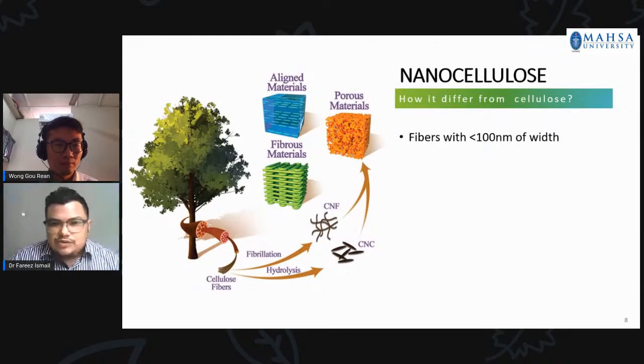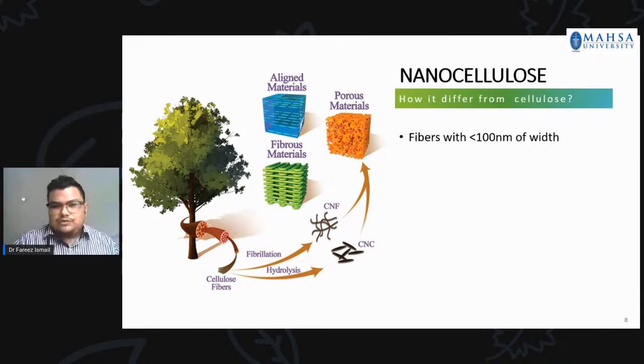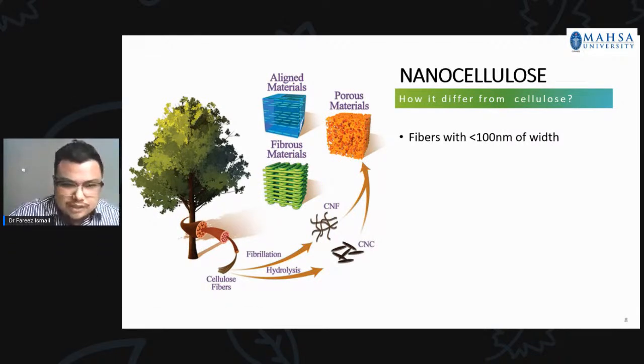So now looking at nanocellulose, how does it differ from cellulose? Looking at the image here, a single plant cellulose fiber, with a width of 30 micrometers and a length of 1 millimeter, consists of numerous cellulose microfibers. And nanocellulose is actually prepared from the plant cellulose fiber via a few processes. And because of the numerous hydrogen bonds present between the cellulose microfibrils,